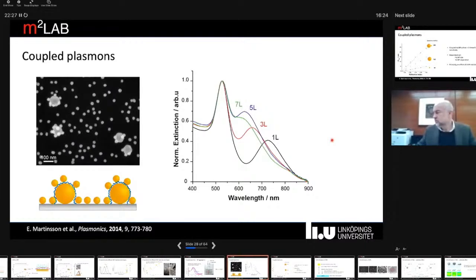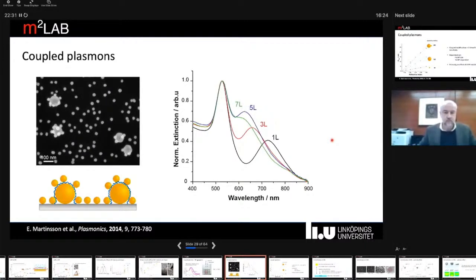But we can still employ plasmonic coupling to redshift the plasmon band if we do this in a more defined way than just unspecific aggregation. And we can do it by essentially making satellite structures of smaller and larger particles separated by a well-defined distance using polymer layers, as in this case. And we can see that we go from one very distinct plasmon band to essentially several different plasmon modes due to this plasmonic coupling. And we can see that we redshift the second plasmon mode more the closer the particles are to each other. So with just one polymer layer, we have a very well-defined second plasmon band that we can use for sensing.